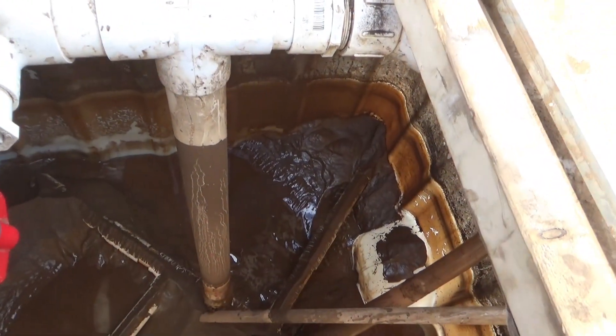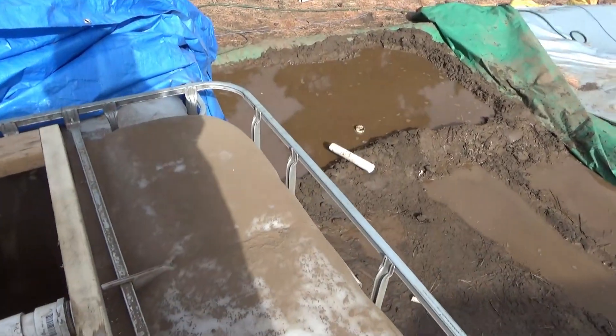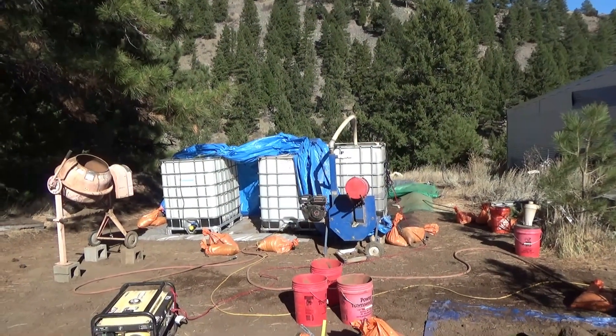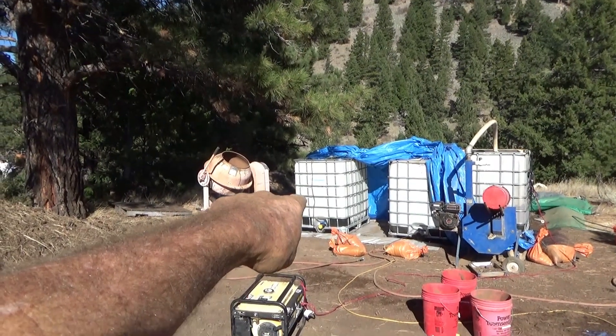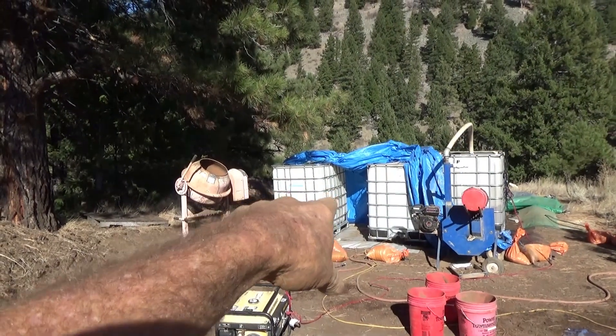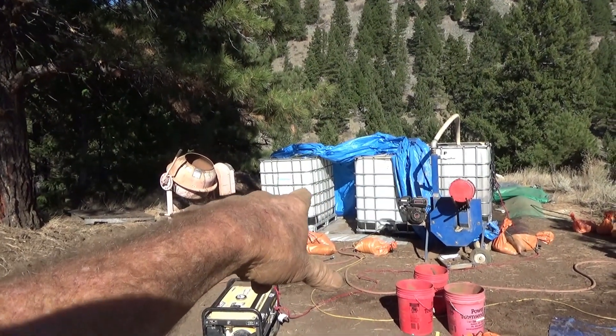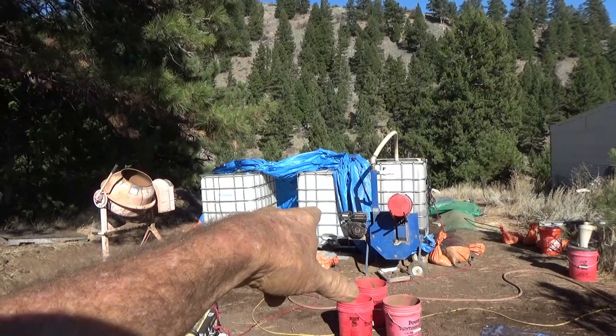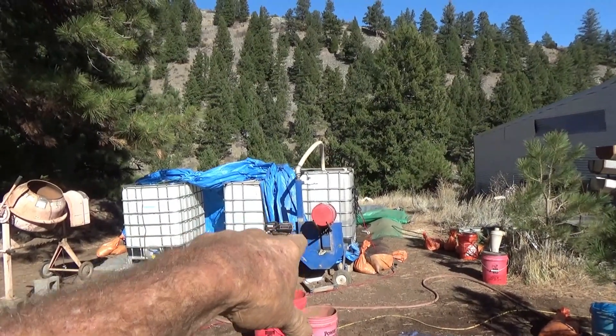Anyway, I'll see about washing this out and getting it draining into the pregnant pond. Once we've recovered the solution from the tailings pad, it winds up being pumped into that tank there — that would be called the pregnant tank, it's the one with the gold in it. Between those two totes, that gap will hold the resin adsorption system — you can think of it kind of like a filter, but it's not. And there's your barren tank — that's the one without the gold in it. From there, it'll be pumped into the agitation tank, ready to receive the next batch of ore.